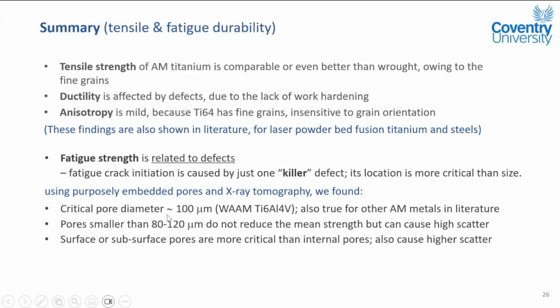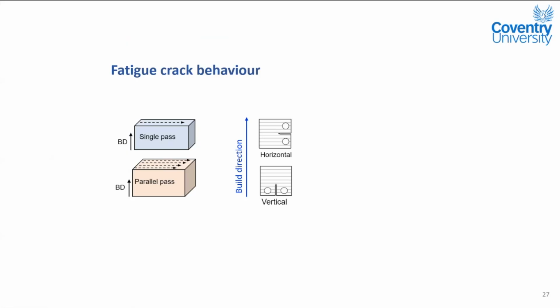So for our material, we show this is around 100 micron in terms of diameter by fractography. And this broadly agrees with other people's findings. And so I think I will quickly move to my final testing, which is the fatigue crack growth behavior. So we have these very large walls. One is thin for aerospace applications. The other one is thicker for energy sectors.